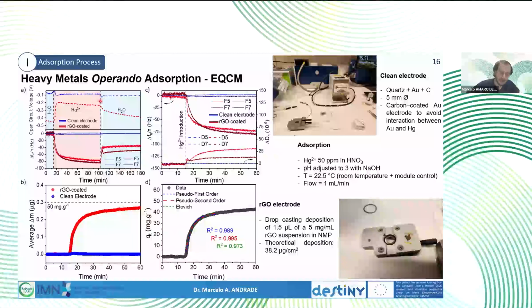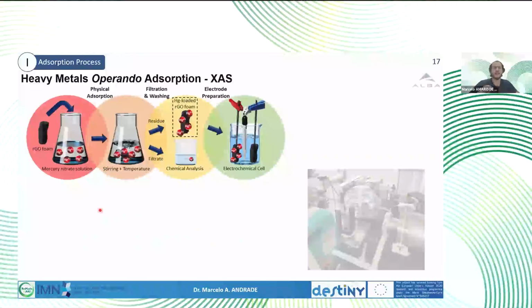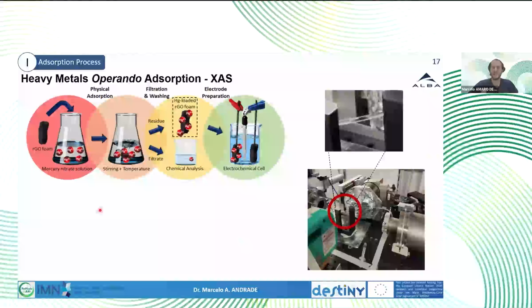And then I was flowing water again to see if the mass would come back to its original state. But that was not the case. There was an irreversible change, so mercury was indeed adsorbed into the RGO. We could see that in real time with the flowing of this mercury solution. And it was reaching about 50 milligrams of mercury per gram, since we can achieve that by the mass variation on the EQCM. And not happy with only EQCM, that's when we went to XAS.